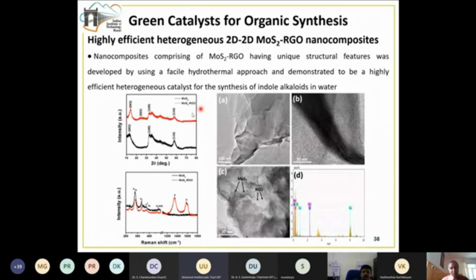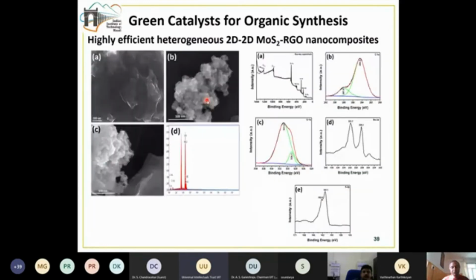We did it using X-ray diffraction and Raman spectroscopic analysis. Then we studied the morphology using TEM, which is shown here, and also SEM analysis to understand the morphology better. And we also did XPS analysis to know the oxidation state of the different elements present in the material, and also the neighborhood environment and their interactions.